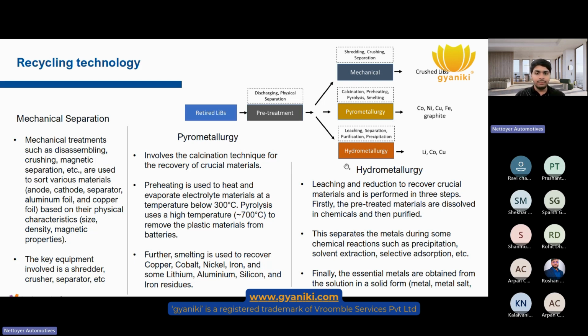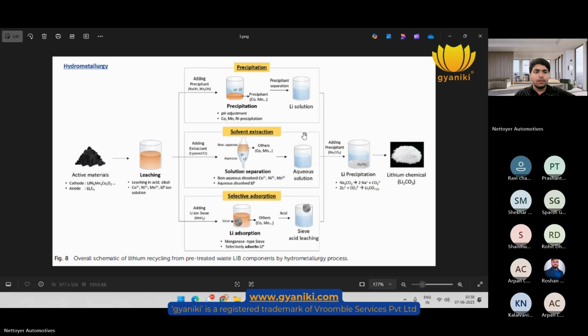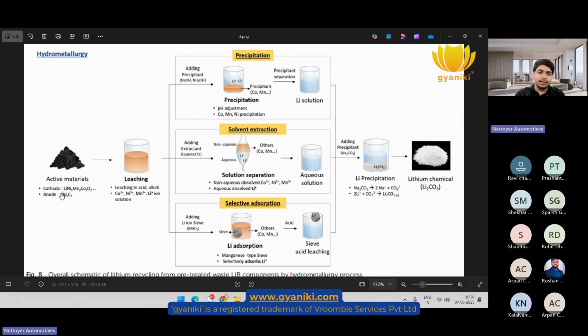So we'll take a look at that as well. So we have active material. Now this active material undergoes the leaching process. There are different acids involved in leaching. After leaching, we have the precipitation process. In the precipitation process, we have the pH adjustment and the overall thing carried out after leaching. After leaching, we get lithium carbonate in the form of precipitate. In this particular process, we get an efficiency of roughly 95% only on a lab scale. When you scale it up, the efficiency goes to about 80%.